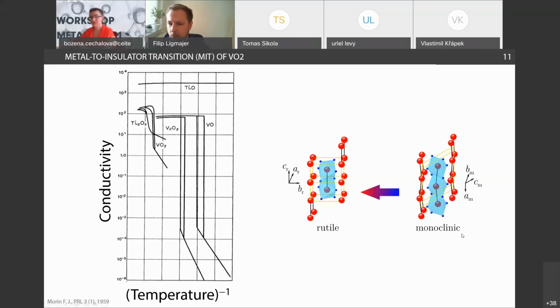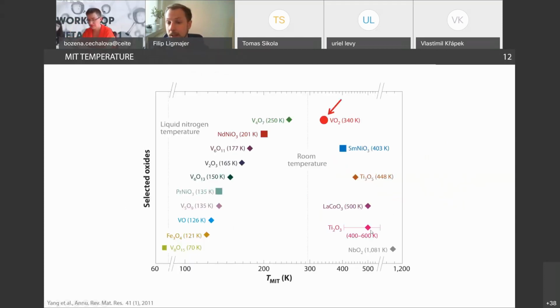So VO2 undergoes transition from monoclinic crystallographic orientation or state into rutile. You see these red dots are vanadium atoms which have this zigzag conformation, and at higher temperatures they just move and align themselves and form the other crystallographic structure. And this subtle motion of atoms and their subtle alignment leads to really large change in the band structure and in the conductivity of the material. And as I said, what's nice about VO2 is that this metal to insulator transition temperature is one of the closest ones from many other materials which have this property, like other stoichiometries of vanadium oxides or some titanium oxides, etc.